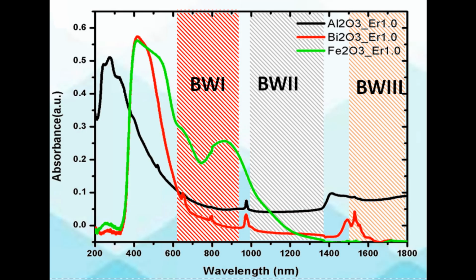In the absorption spectrum, we can see the presence of the erbium ion directly in the bismuth and aluminum oxide, due to peaks at 980 and 1550 nanometers, the absorption at 808 nanometers in the bismuth oxide matrix also being very visible. For its part, iron oxide is the sample with the least evidence of the presence of the ion, possibly hidden under the absorption of the same matrix, but with a slight presence in the 1550 nanometers area.